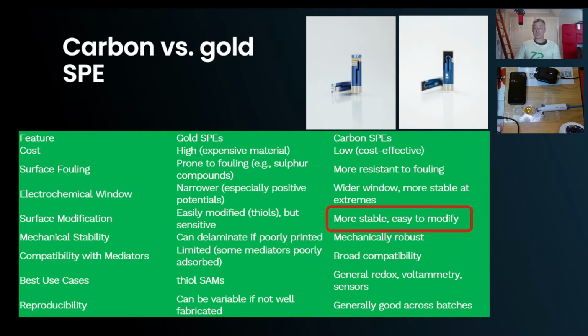But I would also say that carbon is just as easy to modify. You see plenty of papers where they take the carbon surface and they oxidize it so it's got more oxygens on the surface, and then they use things like EDC, NHS coupling. They can couple to the surface using amide bonds. We've used pyrene NHS a bit.